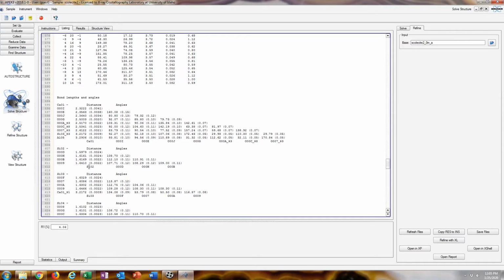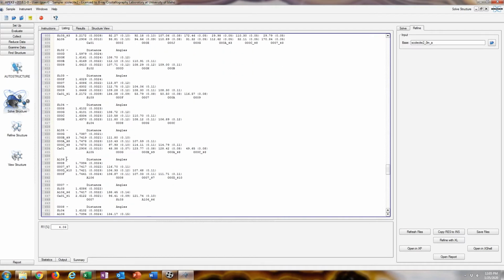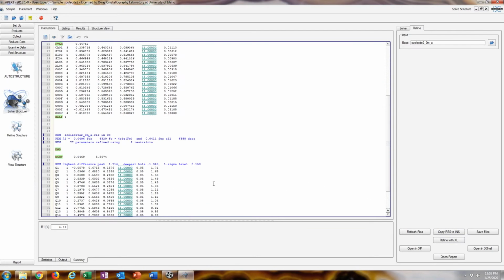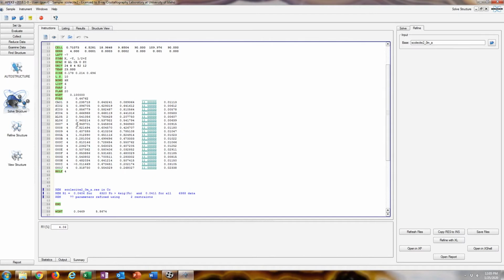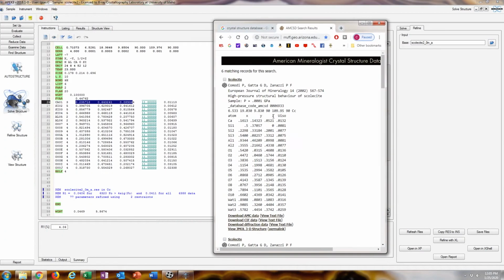That's good. That makes sense. All the Si are about 1.6 angstroms from oxygens, so that works. The aluminum's 1.7. That all makes sense. So it really did find the correct atom assignments in this example. Sometimes if you have magnesium in the structure, it'll mix that up with a calcium, and that is pretty obvious. Mg-O should be about 2 angstroms, Ca-O is about 2.3.